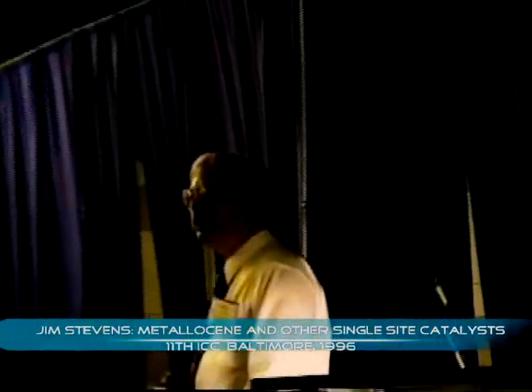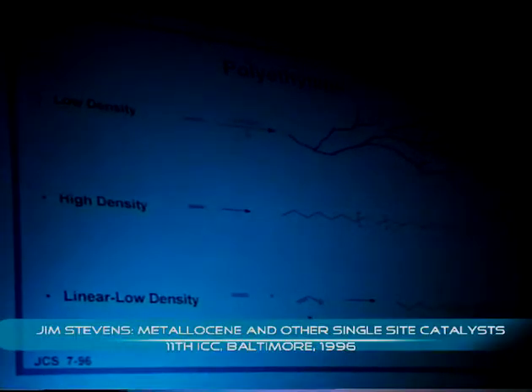Because this is mostly a heterogeneous conference, I thought I'd better take just a few minutes and talk about what the different polyethylenes and polyolefins are. I'm going to focus my talk on polyethylene because that's where the majority of our work at Dow has been. There are really three major kinds of polyethylene up to this point. The first kind commercialized was low density polyethylene, made in an extremely interesting process that's been around since about the 1930s, where ethylene is compressed to extremely high pressure — say 30 to 40,000 psi. Radicals or oxygen are added, and basically a controlled detonation takes place in either a tubular reactor or a tank reactor. Because there are radicals running all over the place at very high temperature, you get a lot of radical recombinations and end up with a very dendritic-like material — like a tree root — called low density polyethylene. That's been a huge volume business for a long time.